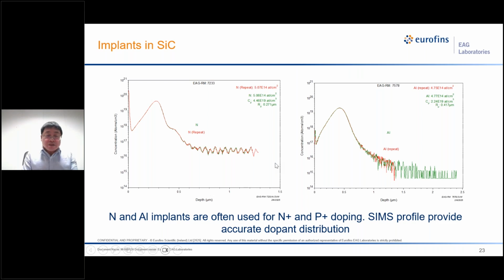One important thing for SIMS is implantation. Here is the SIMS result for nitrogen. There are questions related to what the SIMS artifact is, so here I will talk a little bit about the artifact. You can see here the very high concentration from the surface. That's the SIMS artifact. It's not real. It's from the sample handling, mostly from surface contamination, and also from the atmospheric species. I will talk about this one a little bit later.